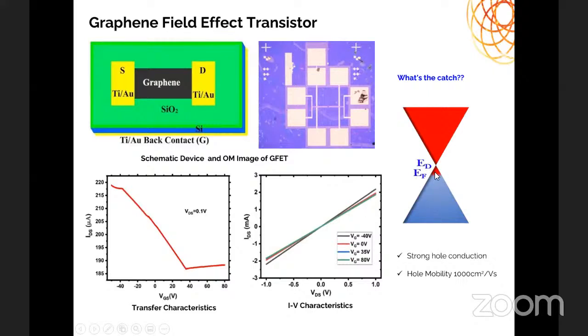Here, this device's results confirm that the Fermi level is close to the valence band, not at the Dirac point. That means it's a p-type material. The graphene is p-doped. In general, p-doping in graphene is usually expected in a CVD-based approach, because it involves processes with PMMA residues and water molecules, which may induce additional doping that shifts the Fermi level.